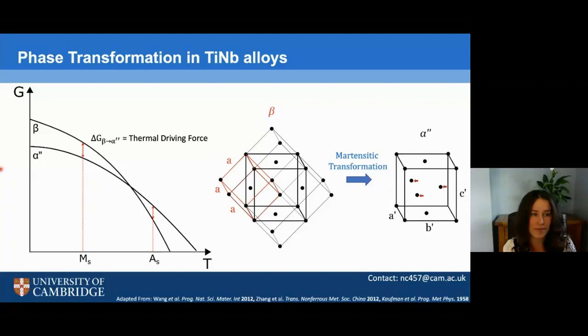However, in the literature widely different values of MS have been reported even for the same alloy. A number of things could account for this variation, such as grain size, specimen dimensions, loading conditions, and sample preparation, none of which are well controlled or reported within the literature. My work looks at isolating these various effects to see if we can rationalize the behavior of these alloys and ultimately make the behavior more predictable.